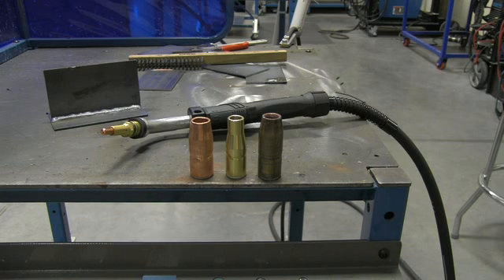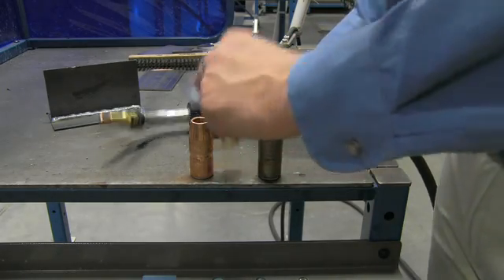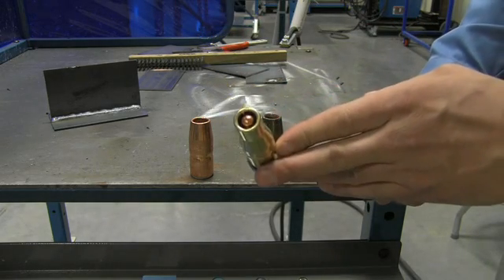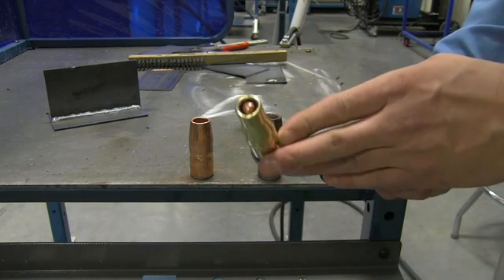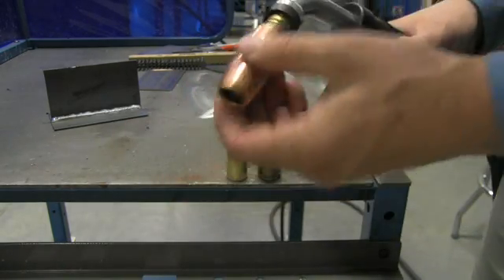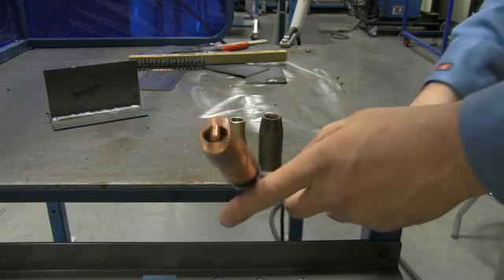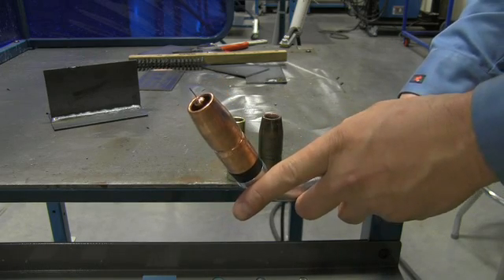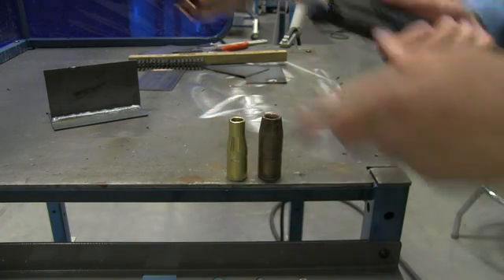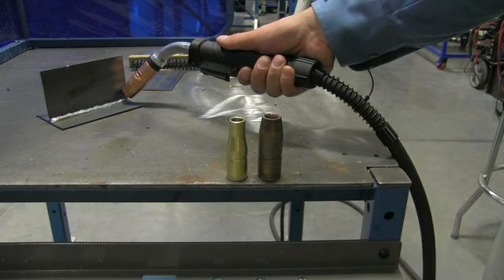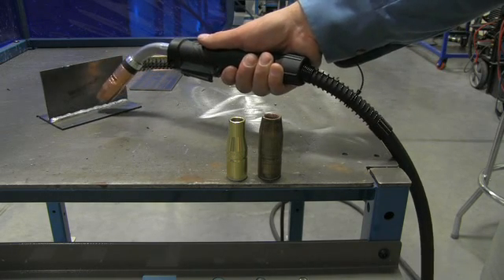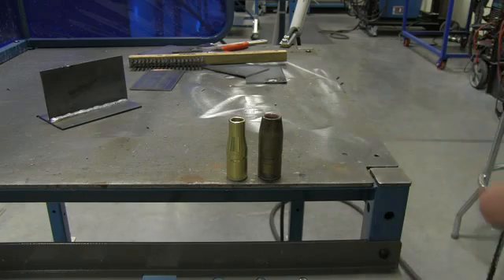Now, to ensure that you can maintain this electrode extension, it's important to have the correct contact tip to nozzle configuration. So for short circuit transfer, we like to use a flush or extended nozzle. And when I say that, this is what I mean. This means that the contact tip sits flush with the end of the nozzle. This helps us maintain that shorter stickout so we can have a stable arc transfer. Okay. Also, we can use an extended up to 1/8 inch. And so see here, you see with this nozzle, we can have the contact tip extended. And so what this does is allows us to get closer to the weld pool to maintain that 1/4 to 3/8 inch.